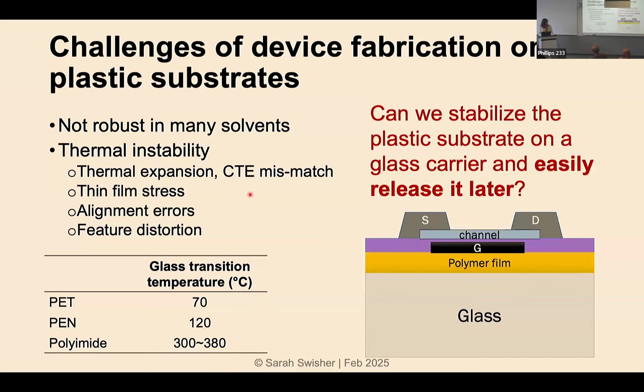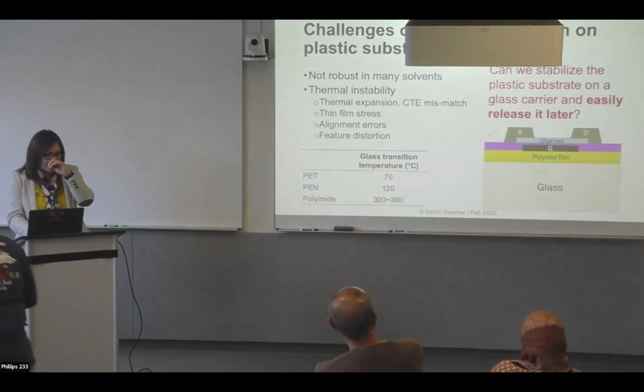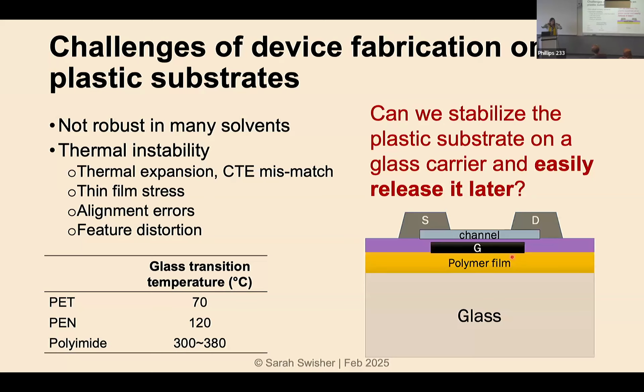There are already methods like the laser liftoff that I mentioned, where you use the strategy of basically stabilizing the plastic film on a glass carrier. So this is, for example, a spin-on polyimide film. And then you would fabricate your devices fully on top of that plastic film while they are supported by the glass carrier, and then release it later. So there are different methods of doing that.